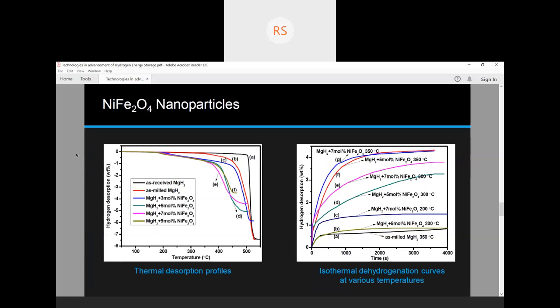Here there are different profiles of the samples at different temperatures and different doping of the catalyst. From figure 1 we can observe that nickel ferrite nanopowder can significantly enhance the desorption performance of magnesium hydride, as the onset dehydrogenation temperature of the doped sample is reduced compared with the pristine MgH2. The pristine sample commences to release hydrogen at 441 degrees centigrade, which is much higher, while the ball milled MgH2 starts to desorb at 350 degrees centigrade, which is almost 91 degrees centigrade lower than the earlier system.